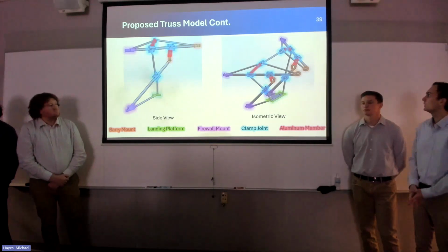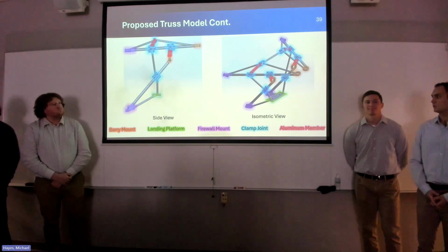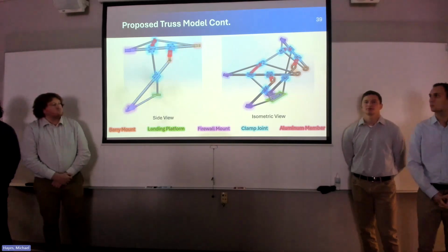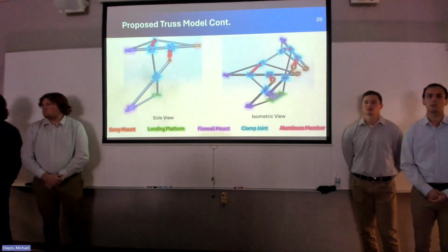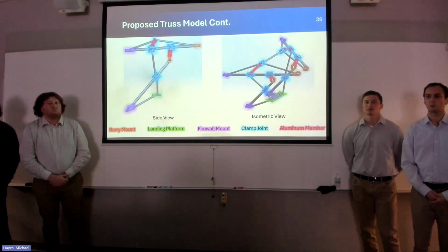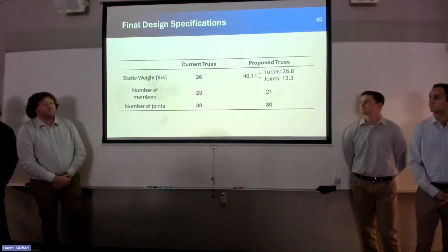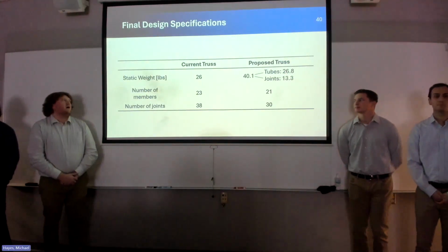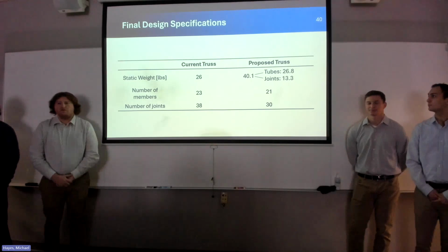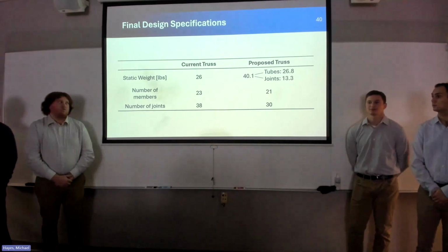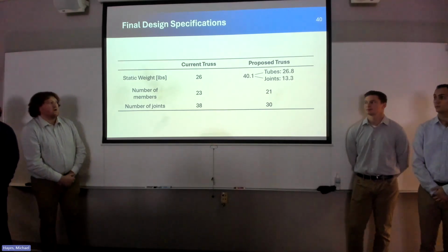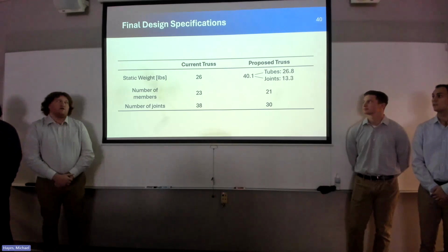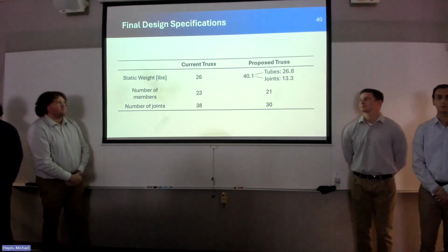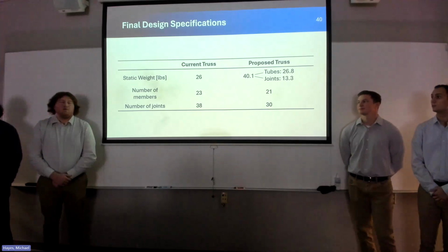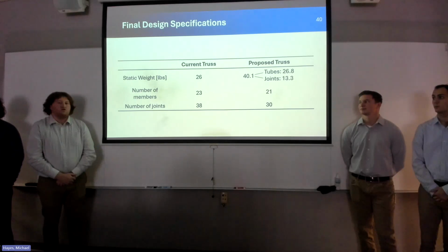In the isometric view here, you can see that the truss is still fully symmetric about the midplane, and we wanted to do that to increase the ease of manufacturing and assemblability. So for some of our final design considerations, the current Delta Hawk truss does have a static weight of about 26 pounds. Ours is currently way above that at 40.1, which we did not meet the objective of the 20% weight reduction. However, we have not weight optimized the tubes or the joints.